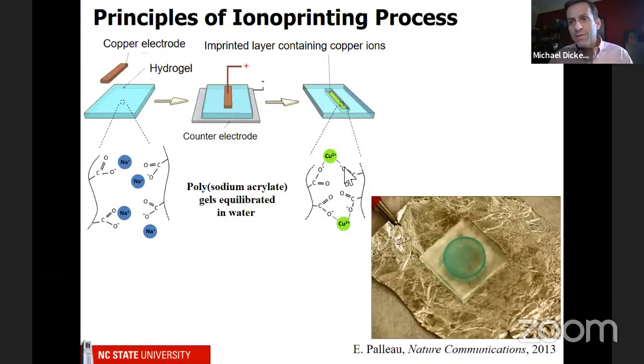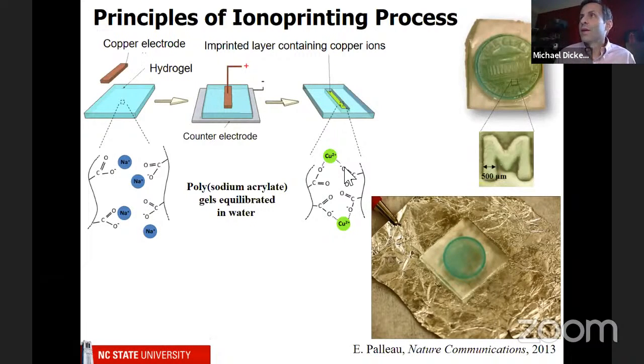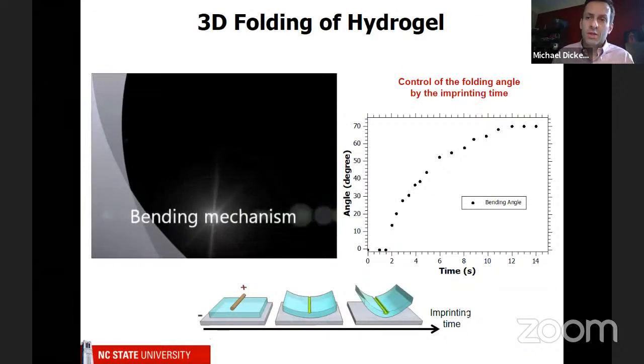So this effect can actually generate stress. Basically, it pulls those polymer chains together. Now you can see that it replicates not only the color that you would expect, but it replicates the topography or the shape of the penny. And that's because those copper ions bond so strongly that they don't diffuse away. Normally, when you put ions into salt, they will just solvate and diffuse away. These stay in place for months at a time. It's really remarkable. And so we've used this to create stress.